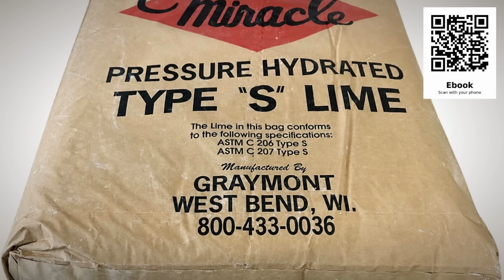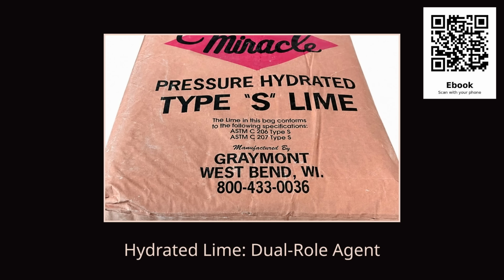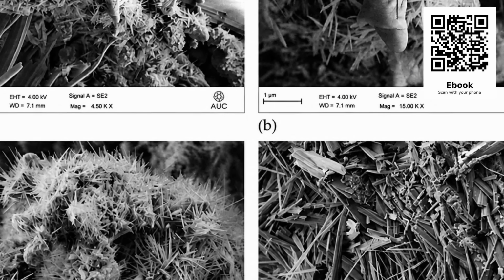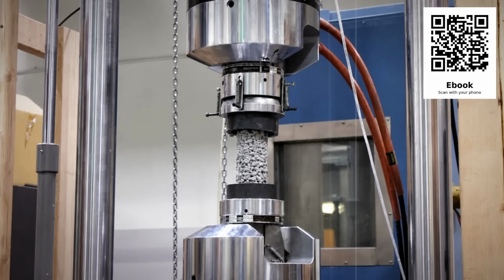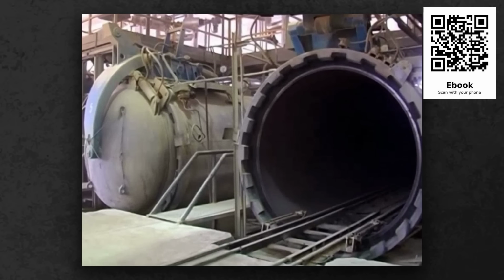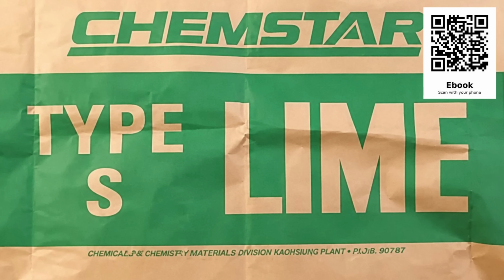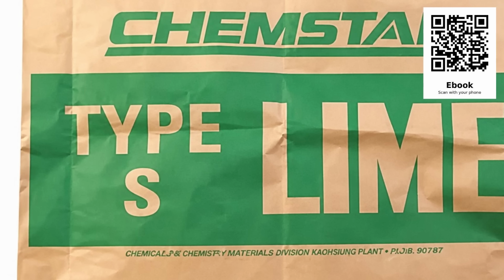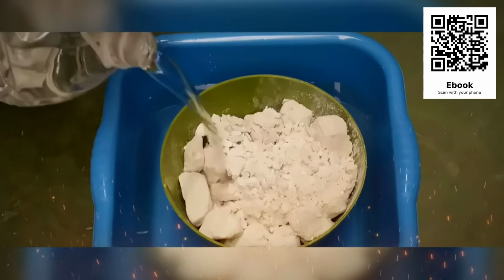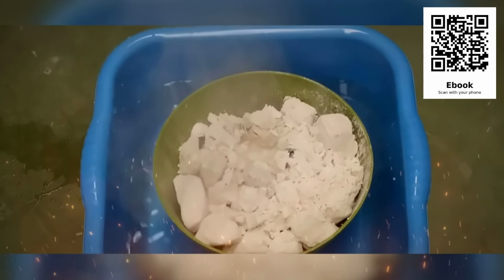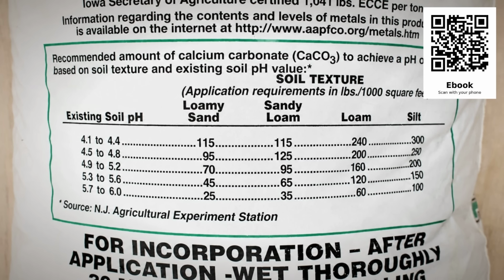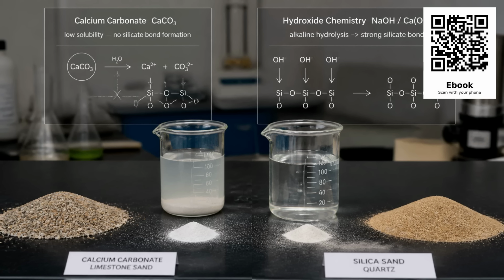The lime I mentioned in the main recipe, hydrated lime or calcium hydroxide, serves a dual purpose. It contributes calcium ions that help form additional crystalline phases within the silicate matrix, increasing strength and durability. It also acts as a mild setting agent, accelerating the cure slightly. Use type S hydrated lime, the same product sold for masonry mortar. Do not use quicklime, which is calcium oxide, because it reacts violently with water and can cause burns. Do not use agricultural lime, which is calcium carbonate, because it does not have the same chemistry.